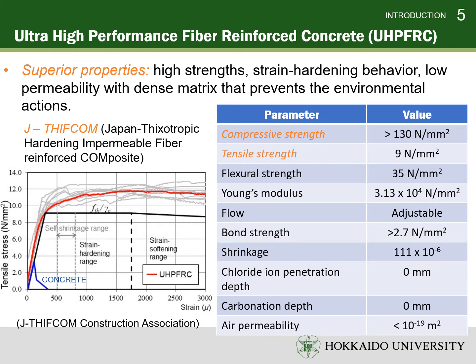Compared to conventional high-performance cementitious material, ultra-high-performance fiber reinforced concrete (UHPFRC) exhibits more excellent properties such as very high strength under both tension and compression, as well as strain hardening behavior in tension that is expected to improve the overall stiffness by reducing the stress level in the steel bridge deck. Moreover, a highly dense matrix of UHPFRC provides the material an extremely low permeability, which means the UHPFRC overlay can work as an erosion protection layer against severe factors such as water and chloride ion.